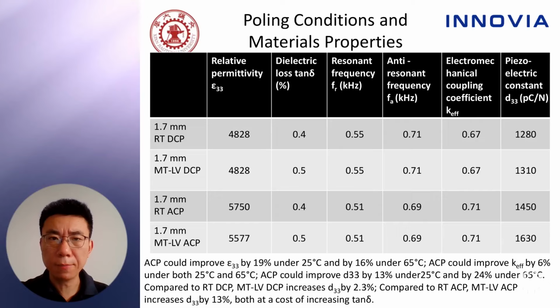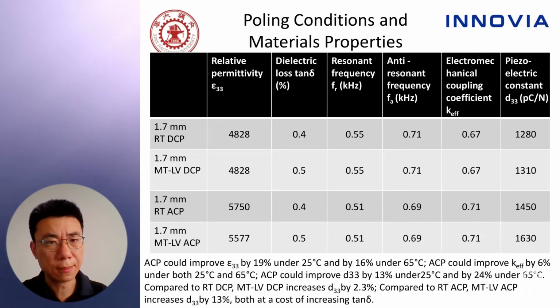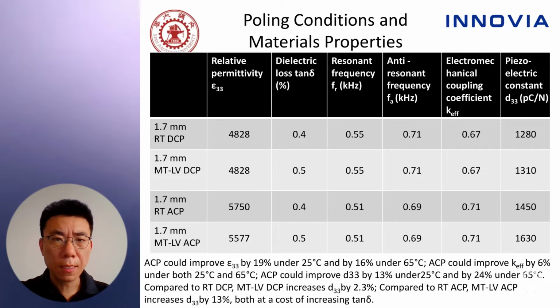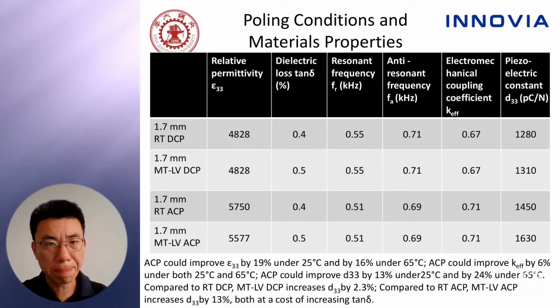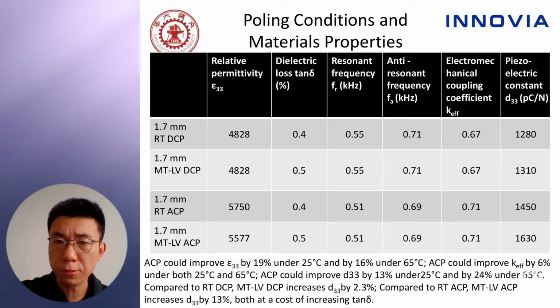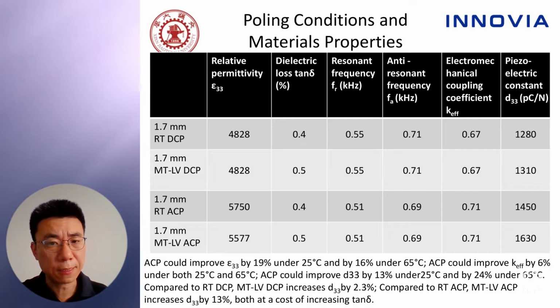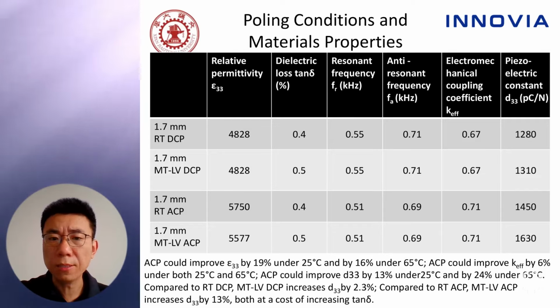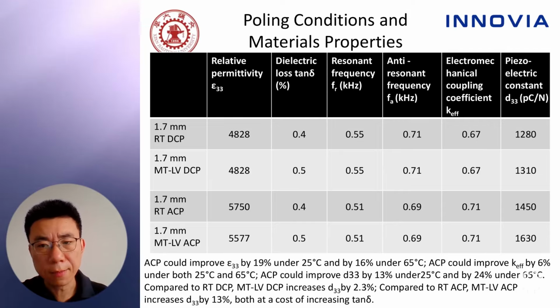Here are the results corresponding between poling conditions and material properties. We are looking at 4 different poling conditions on 1.7 millimeter crystals. The properties we're comparing are relative permittivity, dielectric constant, resonance frequency, anti-resonance frequency, electromechanical coupling coefficient, and piezoelectric constant, d33. As you can see, if we are comparing the columns down, AC poling could improve relative free permittivity by 19% at 25 degrees C and by 16% at 65 degrees C. It could also improve effective electromechanical coupling coefficient by 6% at 25 degrees C and 65 degrees C. AC poling could also improve d33 by 13% at 25 degrees C and by 24% at 65 degrees C.